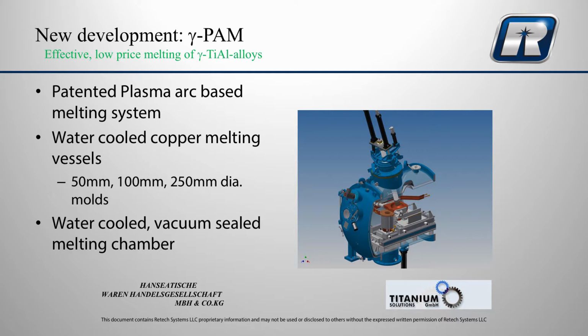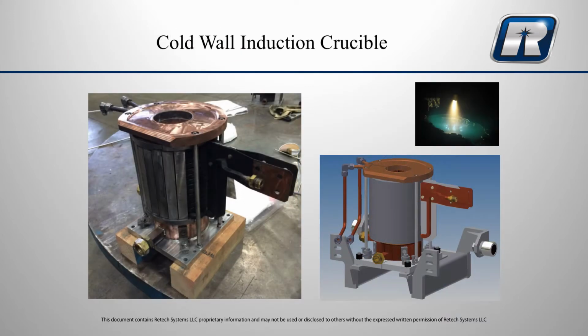All of the melting occurs inside water-cooled copper vessels, and we've demonstrated the melting capabilities at the 50 millimeter diameter scale ingots, 100 millimeter and 250 millimeter diameter molds. Those are existing molds that we have now. There are other size molds that could be made if necessary and if desired. Everything's water cooled inside of a vacuum sealed melting chamber, and melting occurs at atmospheric pressure to retain the aluminum in the material. So just an idea of the cold wall induction crucible.